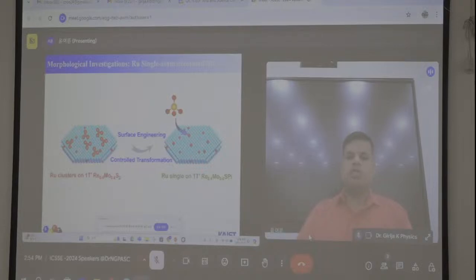But another question you people also raised: why do you choose ruthenium? Because it is a high cost material, but compared to iridium, it is 7 times lower than the iridium cost. And another thing, I am using a very limited percentage, like 2%. I am not using more than 80% or 90%, but I am using single atoms like 2% or 3%. Therefore, I am reducing the cost in a different way.